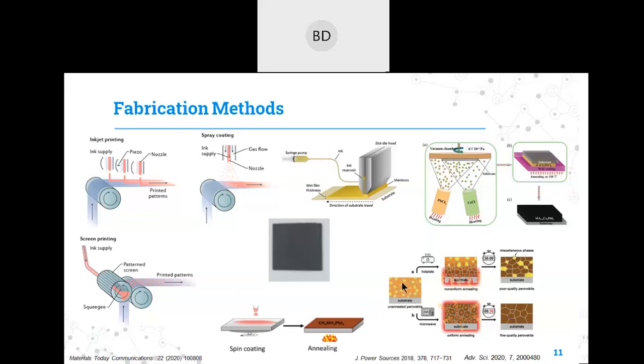But a few groups in China have reported that after depositing the perovskite, you can put it under the microwave for 30 seconds and your perovskite is ready. And if you compare this microwave annealed perovskite with the hot plate annealed perovskite, the microwave annealed perovskite shows better morphological or better crystallization structures. So it has become very easy nowadays to use this process for fabrication.